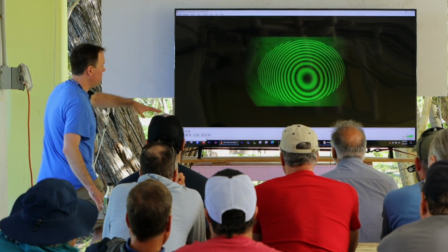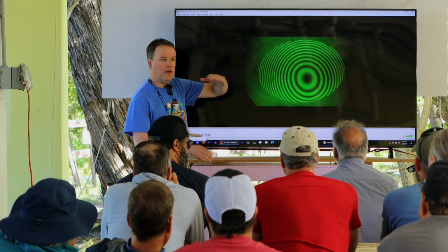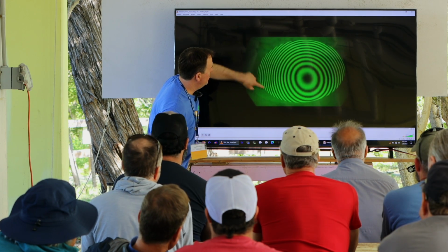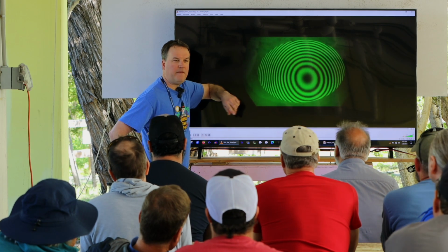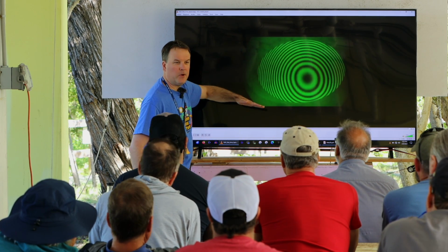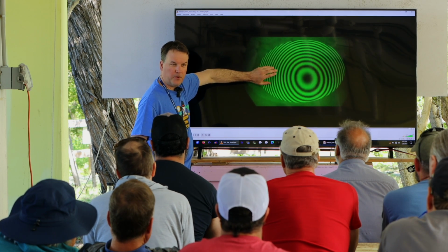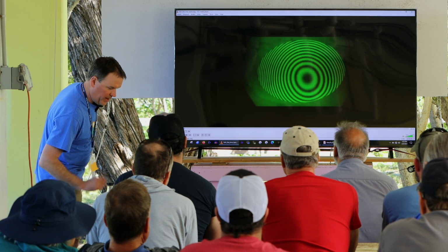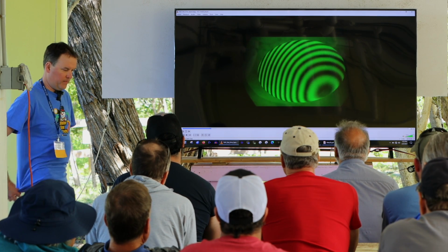So we have basically a surface on the flat that's concave like this, and those interference fringes are half a wave each. So that's the difference between the flat mirror that's not distorting and the Pyrex mirror that is. It's many waves. And then we let it cool off over time.